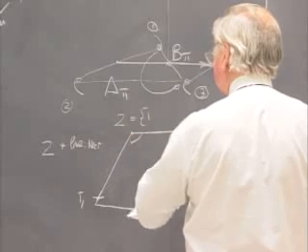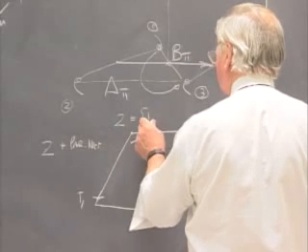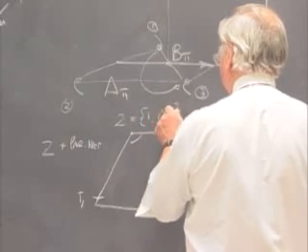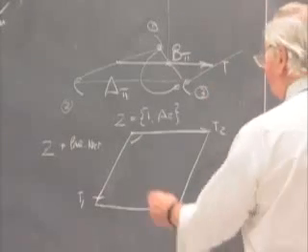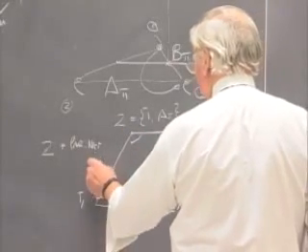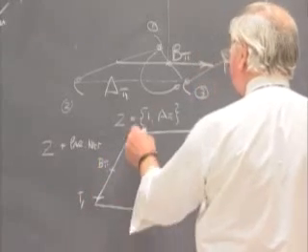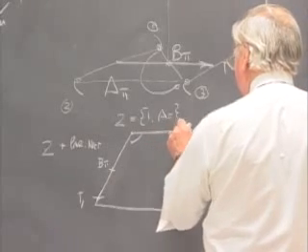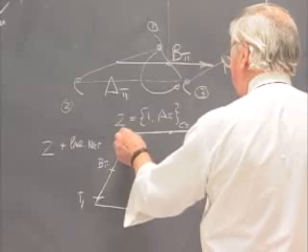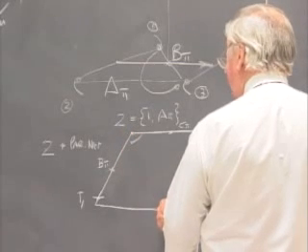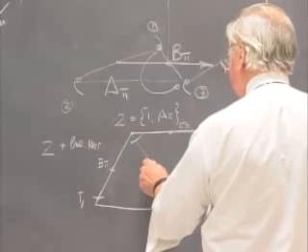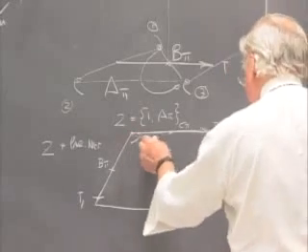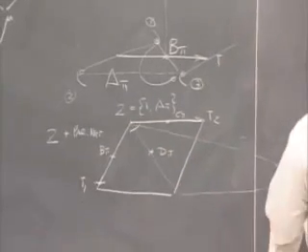A twofold axis involves the presence of two operations, the identity operation, and that we can forget about, and then there's the operation a pi. If I combine a pi with T1, I'll get an operation b pi that sits at the midpoint of T1. If I combine a pi with T2, we get an operation c pi at the midpoint of T2. If I combine a pi with T1 plus T2, I'll get another operation d pi at the center of the cell.